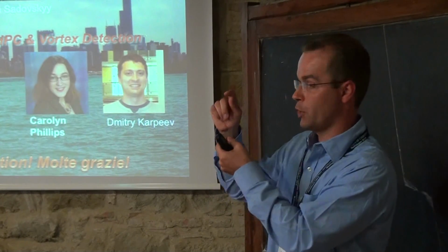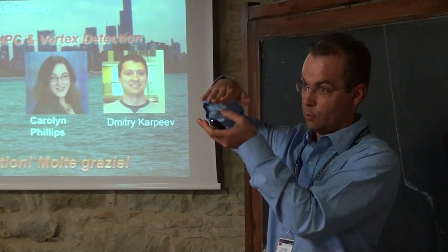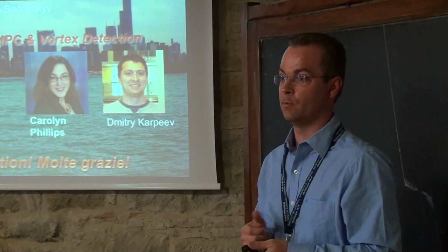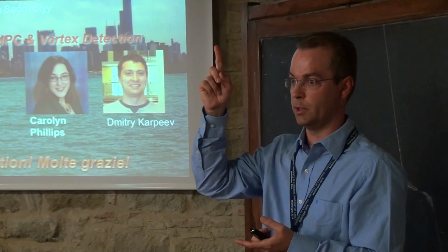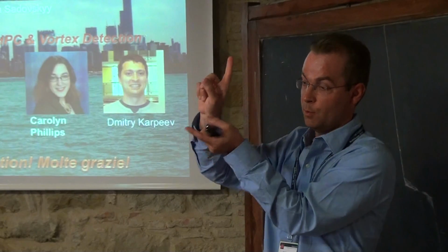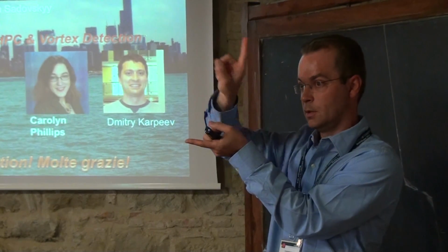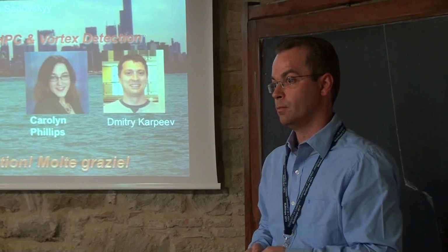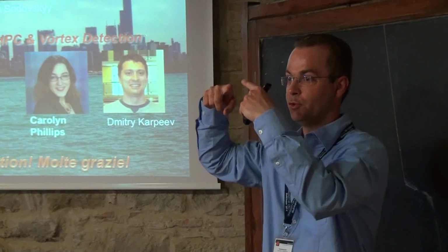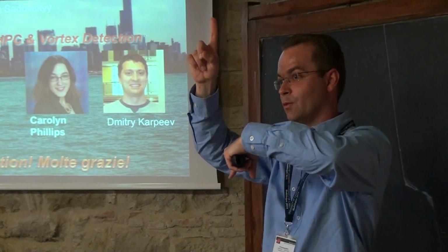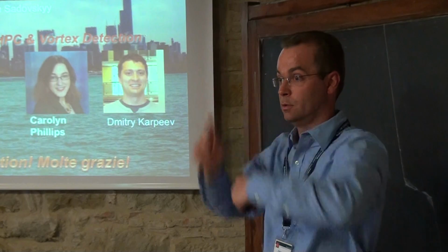And at some point they break, and the ones which are close to the surface go to the surface because for energetic reasons this is more favorable. And then of course the Lorentz forces drag them, depending on their vorticity, to the left or right of the sample. And because you need to preserve the vortex line, you always have vortex, anti-vortex going to these surfaces.